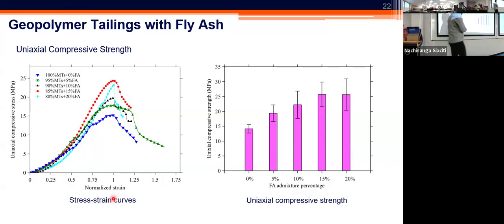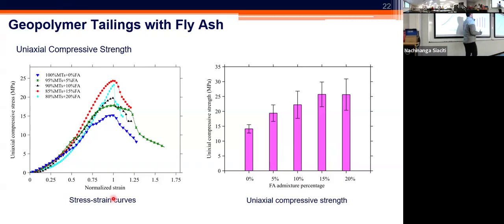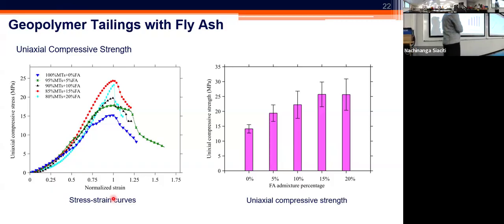So what we saw in this scenario was that even as low as 15% addition of the fly ash can drastically increase the compressive strength of these cubes compared to the control. We saw about 75% improvement in the strength when we used 15% addition of the fly ash. And yes, you might still have some additional improvement, but at least it wasn't very visible or evident to us that it justified the additional use of the fly ash. So we consider the 15% as a sufficient amount of supplementation for these specific tailings.